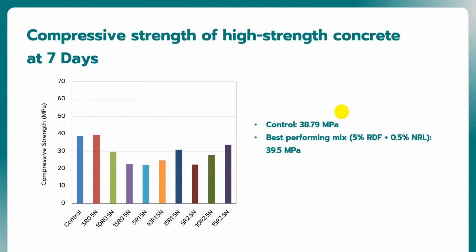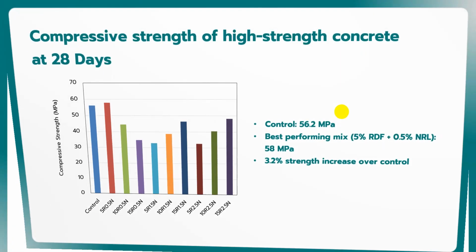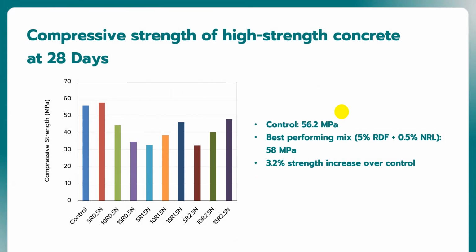At 7 days, we found that the control had 38.79 megapascal, but surprisingly, our material reached 39.5 megapascal, better than the control. At 28 days, the normal high-strength concrete reached 56.2 megapascal, but our new material reached 58 megapascal, which is a 3.2% increase over the high-strength control.